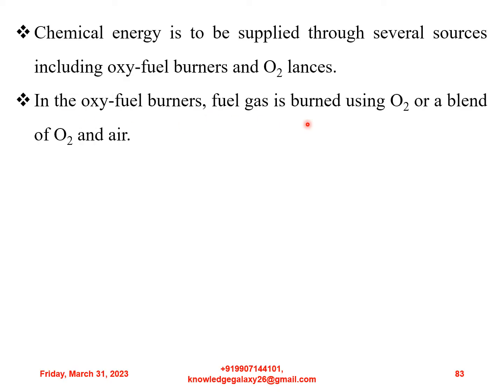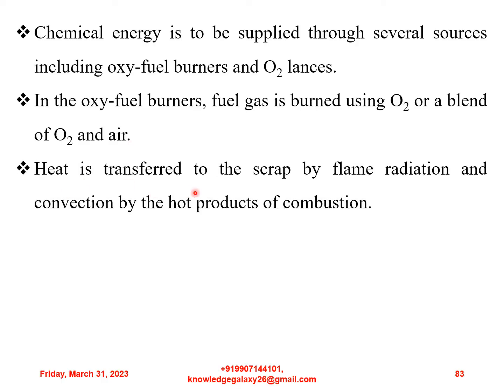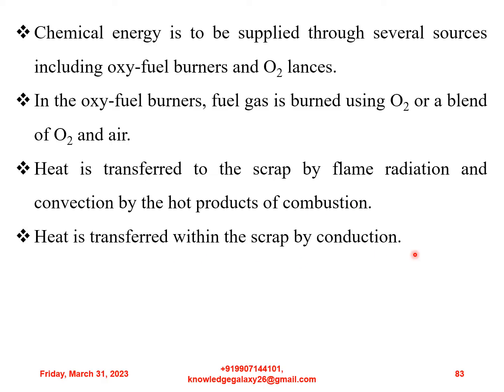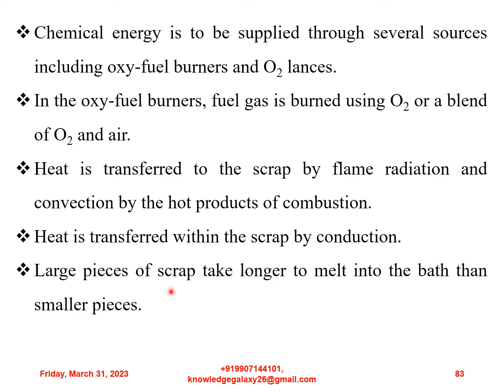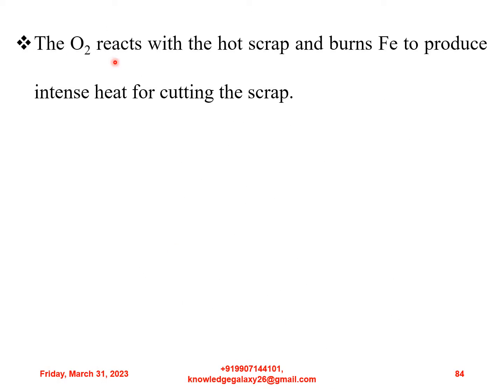In the oxy-fuel burners, fuel gas is burned using oxygen or a blend of oxygen and air. Heat is transferred to the scrap by flame radiation and convection by the hot products of combustion. Heat is transferred within the scrap by conduction. Large pieces of scrap take longer to melt into the bath than smaller pieces. In some of the electric arc furnaces, oxygen is injected through a consumable pipe lance to cut the scrap. The oxygen reacts with the hot scrap and burns iron to produce intense heat for cutting the scrap.